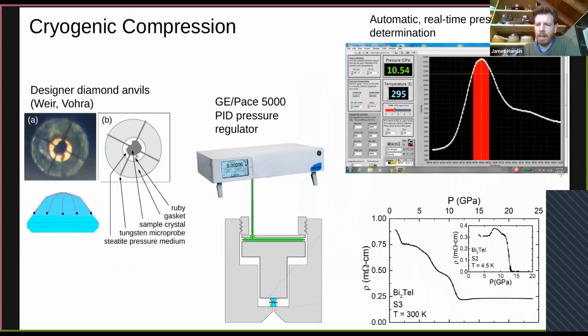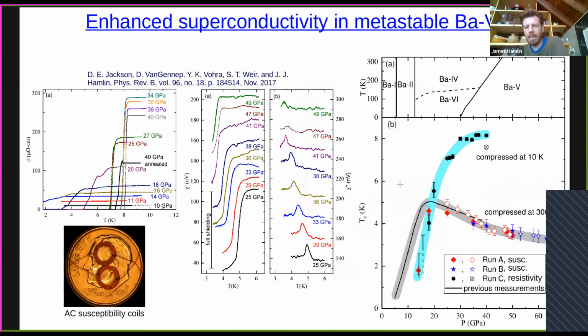We found, if you look here on the right is the phase diagram. So the gray curve is the result that was obtained when you apply pressure at room temperature, kind of the standard approach to these kinds of measurements. In contrast, when we apply pressure at low temperature, we get a significantly enhanced TC. And this was confirmed both in electrical resistivity and magnetic susceptibility measurements. Here are some magnetic susceptibility measurements where you see the transition both in the real and the imaginary part of the data, which is often not shown.